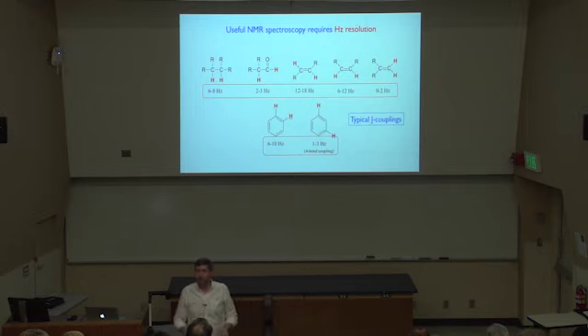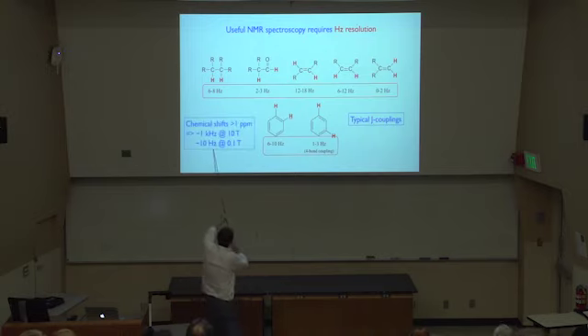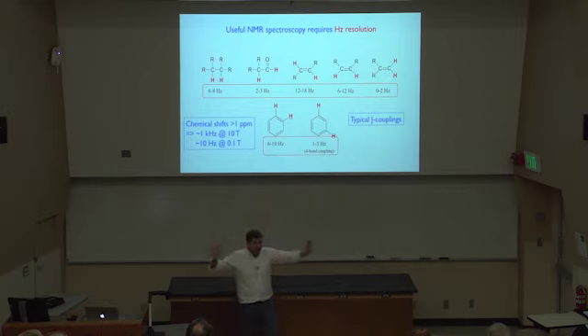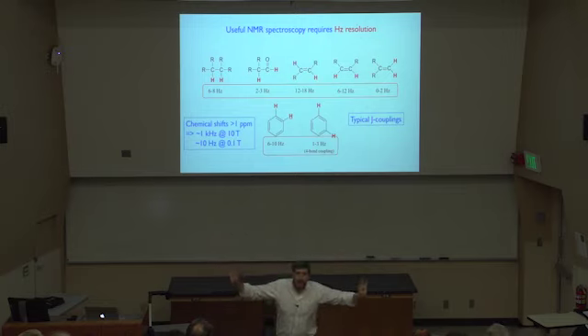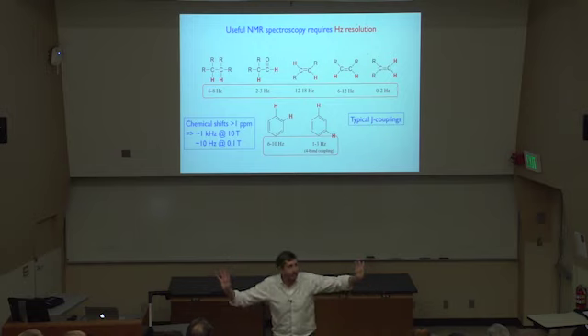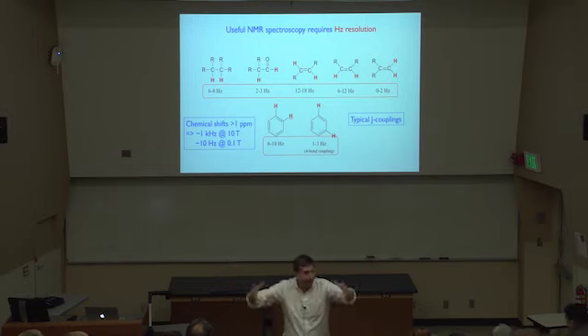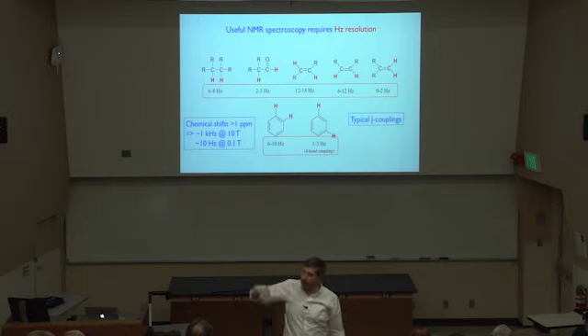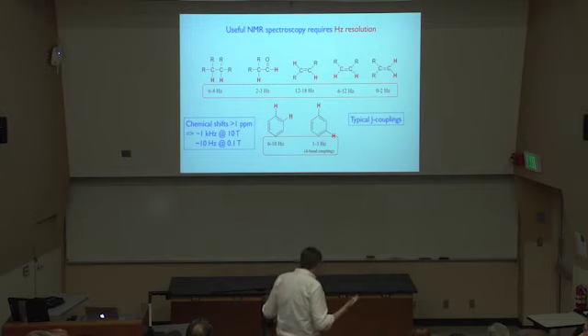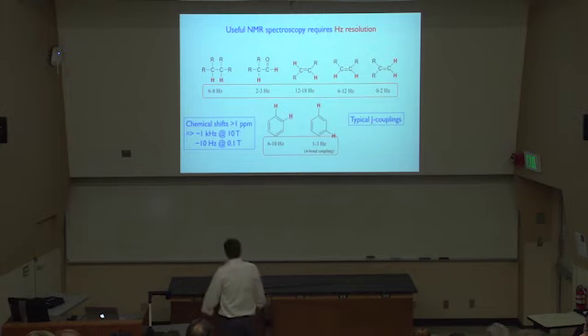Chemical shifts, which are due to either the diamagnetic or paramagnetic shielding of nuclear spins due to their local environment, scale with magnetic field, and they'll go from something on the order of 10 hertz at 0.1 Tesla to much larger at 10 Tesla. So the chemical shifts will split apart, but these J-couplings don't scale with magnetic field to leading order. So if you're going to do state-of-the-art NMR spectroscopy, like they can do on macroscopic samples in a big system in a chemistry lab, and you claim you want to do it at the nanoscale or the micron scale, you've got to do this level of spectroscopy at the hertz level, or you're not doing anything useful, except publishing science papers.